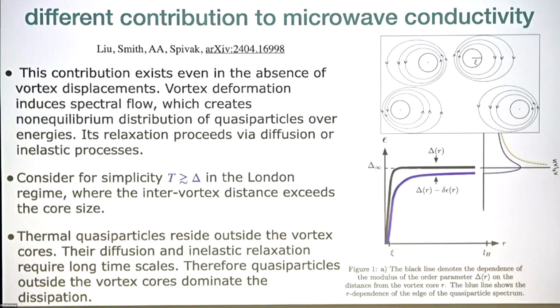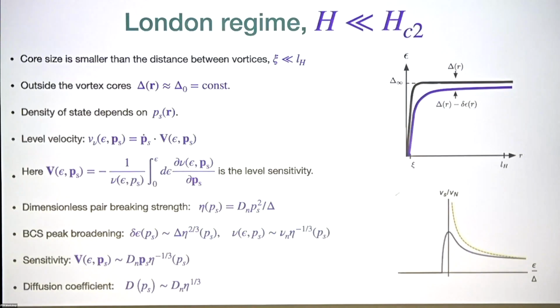you have depairing, right? The density of states is broadened near the boundary of the gap because of the equilibrium currents. Now you apply microwave radiation that induces condensate acceleration. So this flow outside the vortices is changing. So your superflow is sloshing with time because of the presence of the microwave radiation. And therefore, locally, this is called sloshing of the density of states. But now quasi-particles, being normal, cannot slosh together with the condensate. What they feel is this time-dependent non-equilibrium density of states, and they have to redistribute themselves, but they lag with the microwave frequency.